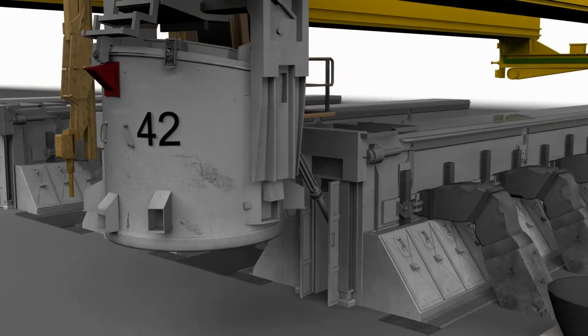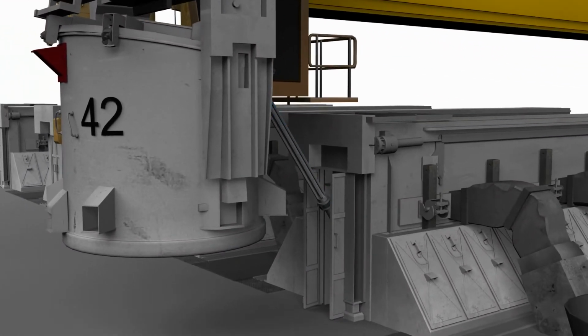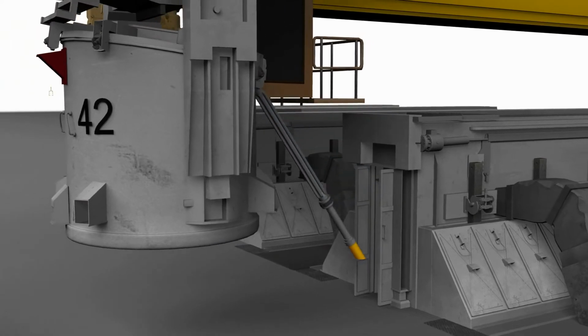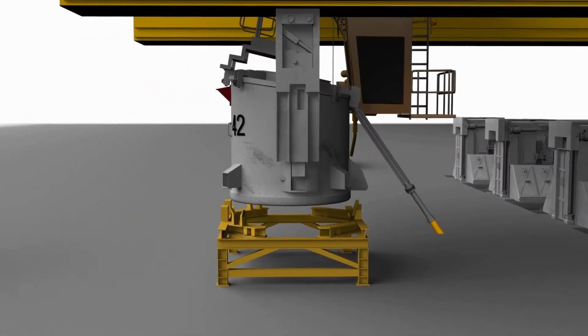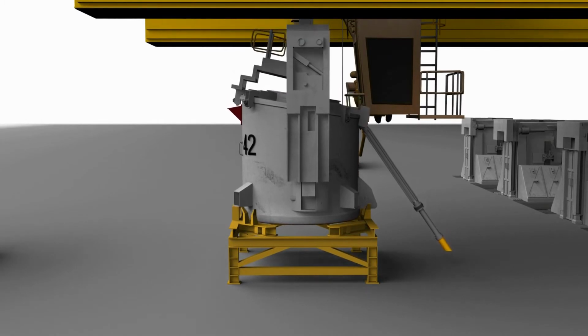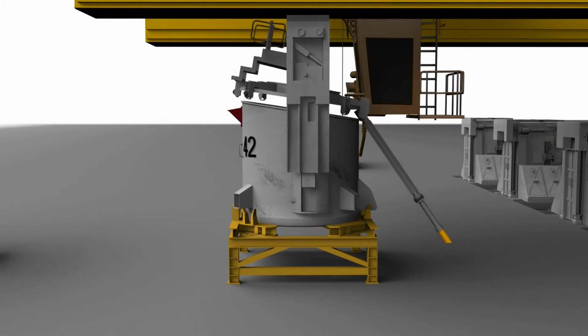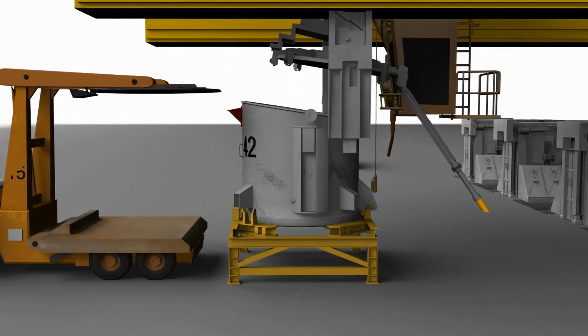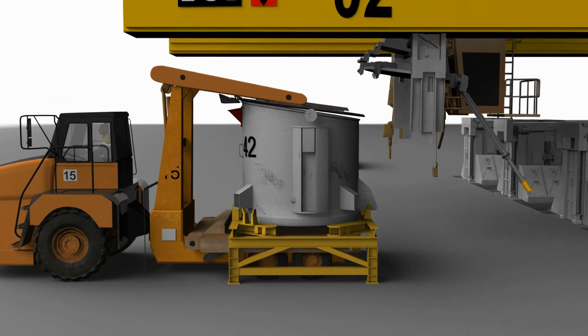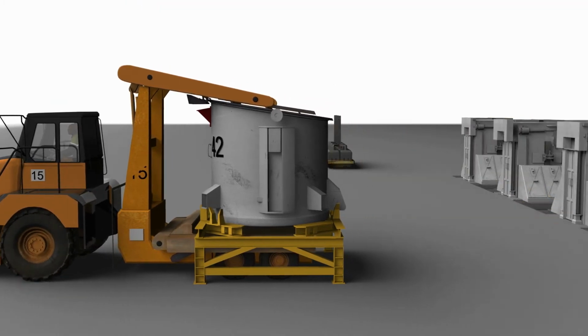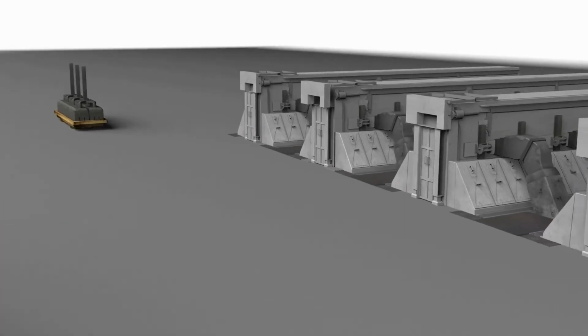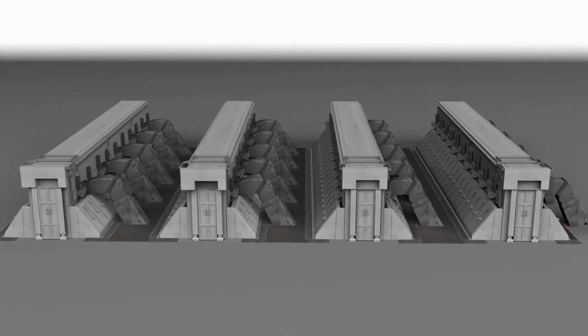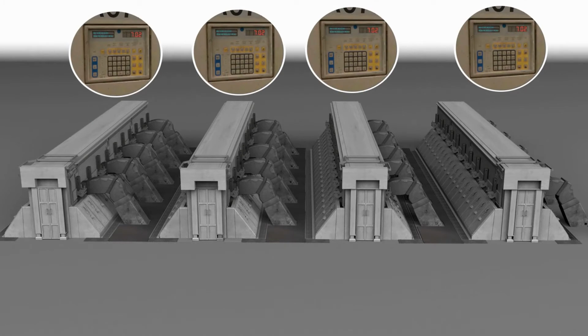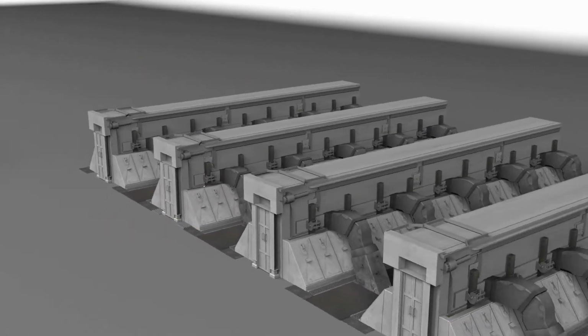Alumina is reduced to molten aluminium, which collects at the bottom of the pot. The aluminium is siphoned out of the pot into a ladle at the rate of 3.2 tons every 32 hours and is transported to the cast house. The addition of fluorinated alumina during the reduction process is controlled by a computer on each pot. The computer also adjusts the anode beam downwards as the anodes are slowly burnt away during the reduction process.